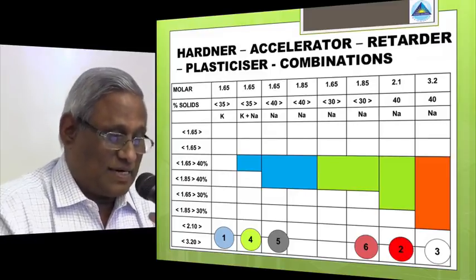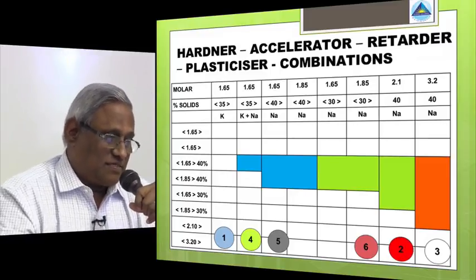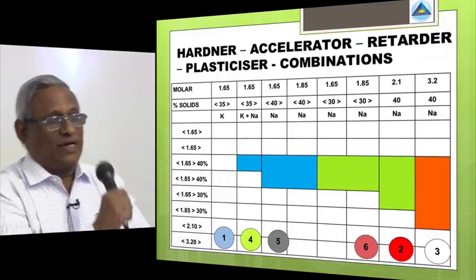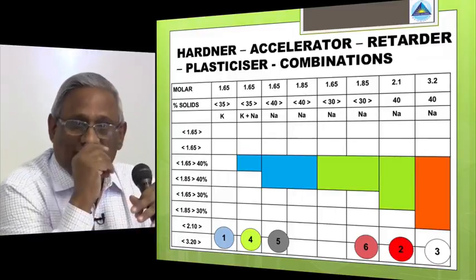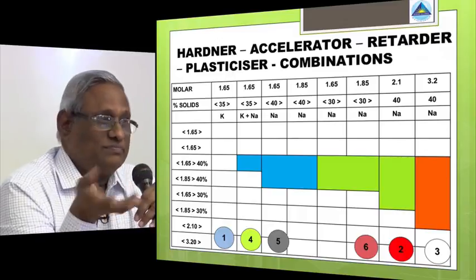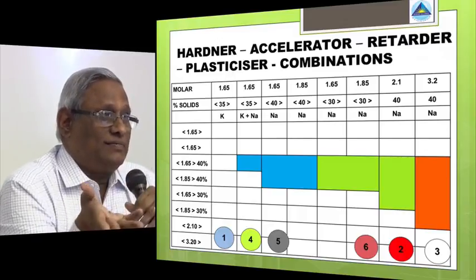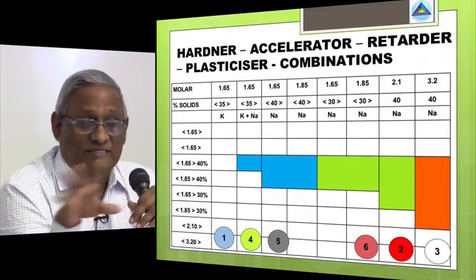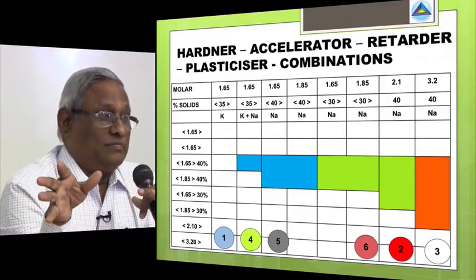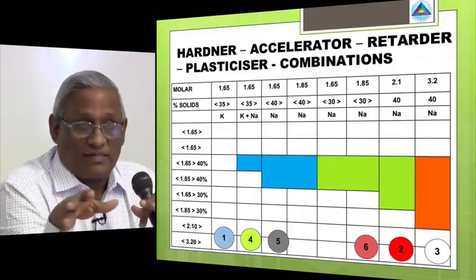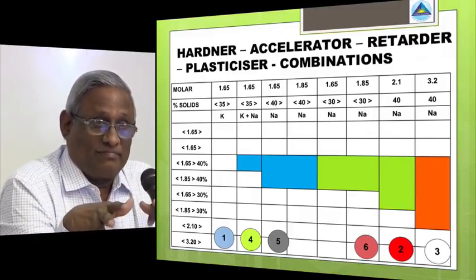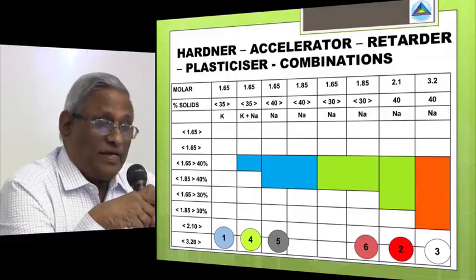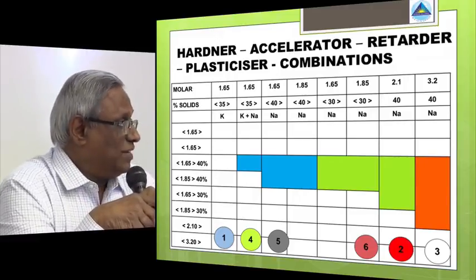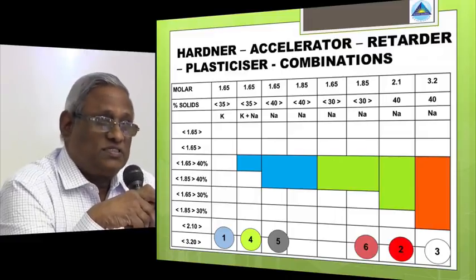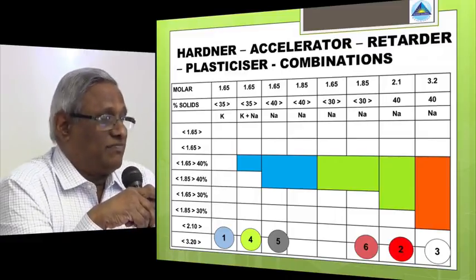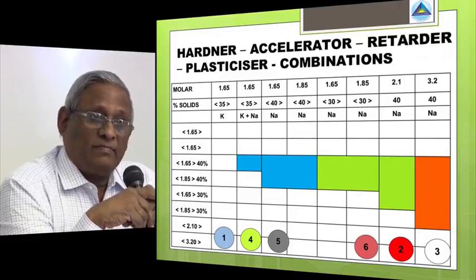Right now, we have made some color charts where in the 40% we have put some blue color, which means you can add water there. You can dilute, add water, for flowability of concrete. We have made concrete, dry mix concretes. We have made self-curing concrete, self-setting concretes. We have made pumpable concrete. The one with the green, you can use it directly. No need of adding water.